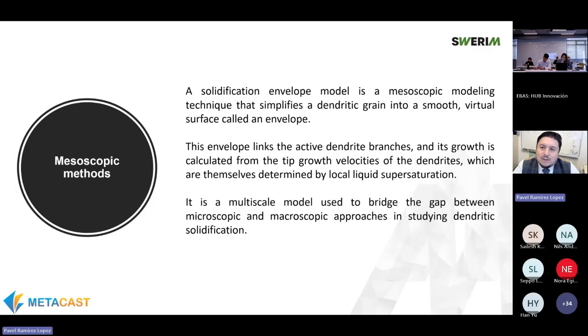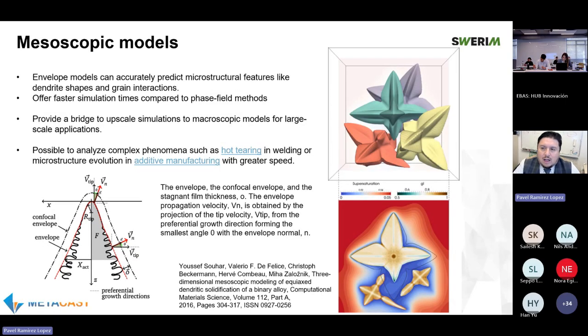The approach is to typically use an envelope that simplifies the dendritic grain into a smooth virtual surface. This envelope links the active dendrite branches, and its growth is calculated from the tip growth velocity of the dendrites, and these are themselves determined by the local liquid supersaturation. It is a multi-scale model, and as I mentioned, is for bridging the gap between micro and macro. For this, I choose as an example this excellent publication by Professor Beckermann and Combeau and their collaborators.